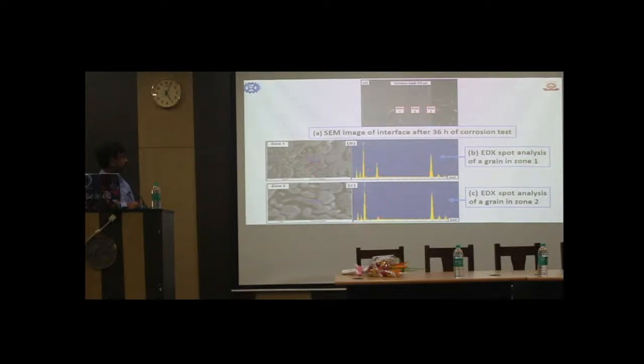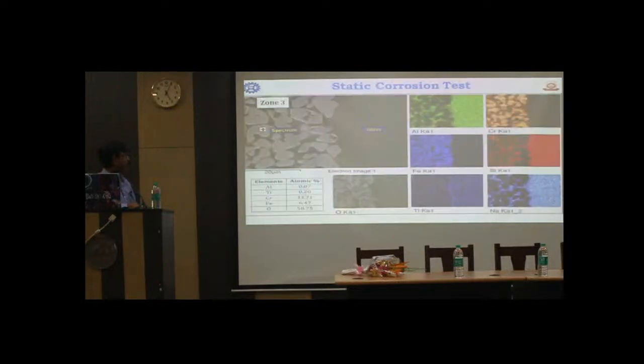That means within the individual grain, this is the aluminum chromium solid solution. Near this region, the aluminum concentration in that grain is less. And if you move towards the glassy phase, the glass region, the aluminum concentration is continuously decreasing. You see the peak, the concentration is less. That clearly indicates from the crystal structure, this aluminum chromium solid solution, aluminum ion is migrating. Now, this is zone 3. Zone 3 is near the glassy phase.